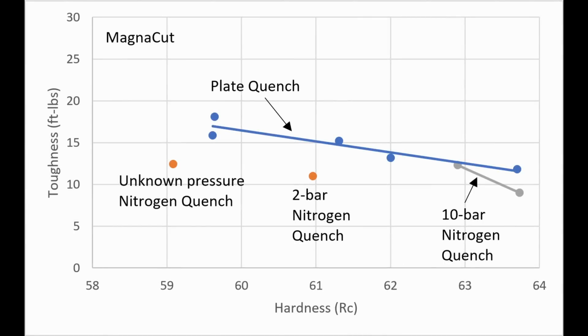I also have toughness data for MagnaCut from 3 different heat treaters that use vacuum furnaces, which I have compared against my own experiments with plate quenching. The 2-bar and unknown pressure heat treaters were targeting the same hardness with the same approximate temperatures. I am not sure of the reason for the discrepancy in hardness. For toughness, both are a similar offset below the plate quench numbers because of the slower quench speed. Presumably, they had a similar quench rate. The slower quench rate led to a reduction in toughness for a given hardness.